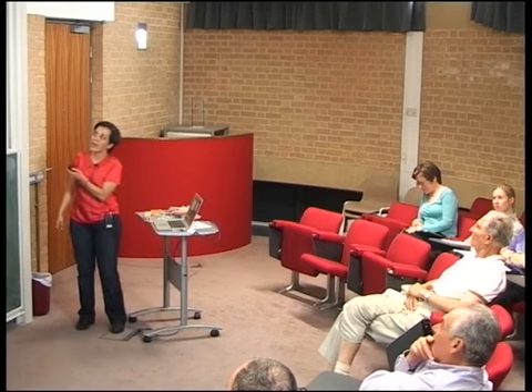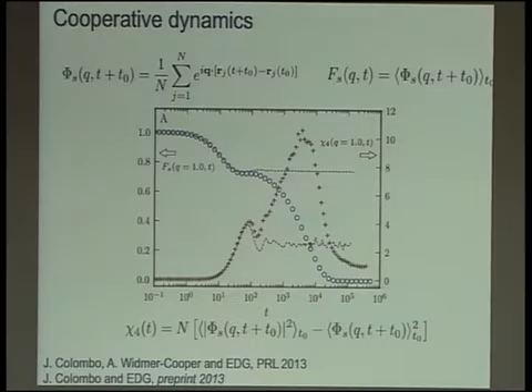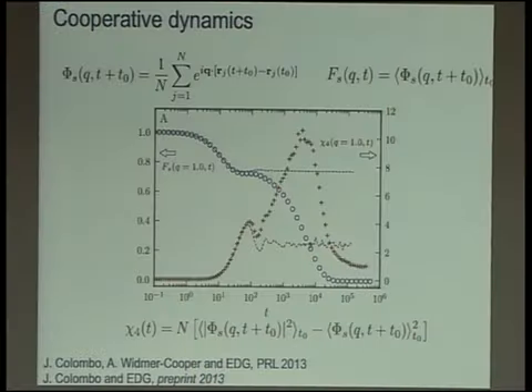And what happens is that this first decay is really determined by the microscopic dynamics, the type of integrators that we use for the type of equation of motion that we use. It's different, but what I'm going to talk about, which is the last part of this decay, will not change. Okay, so the decay from the plateau also is a stretched exponential decay in a certain range of wave vectors. And here what we have done is that in the simulations we have also considered the same network once it's formed, and then we have frozen the bonds. Okay, so we have taken the same initial network and then frozen the bonds so that things cannot break. And then this is the relaxation function that you would measure in that case.